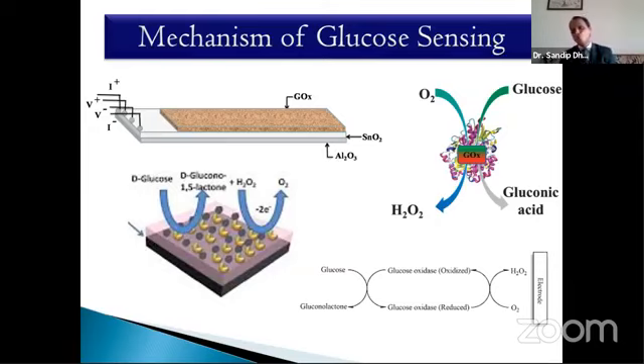So here basically, if this glucose interacts with this enzyme, that is glucose oxidase GOX enzyme, it will oxidize glucose into gluconic acid, and at the same time the oxygen which is present nearby this glucose, normally we have water-based solutions, so the oxygen present in the surrounding is converted into hydrogen peroxide. So at the same time, oxygen gets converted to hydrogen peroxide and glucose gets converted into gluconic acid. During that reaction, two electrons get transferred into this SnO2 surface. The electrons get transferred from this enzyme into the sensor. The resistance of your sensor decreases, and the concentration of glucose is directly proportional to the decrease in the resistance of the sensor. So I can detect this glucose in the form of electrons by using this enzyme. If the enzyme is not there, it will be very difficult.